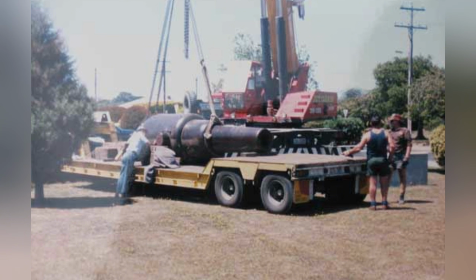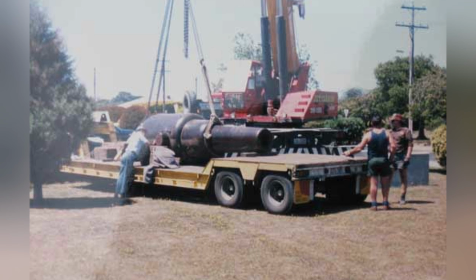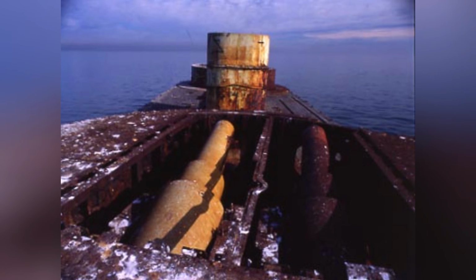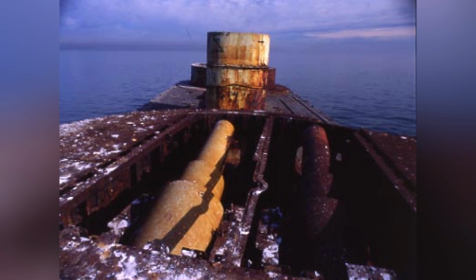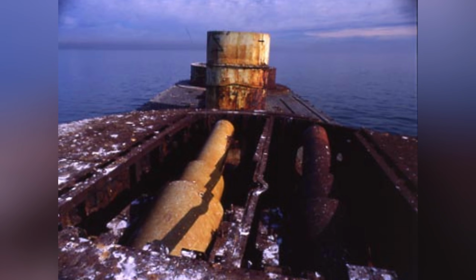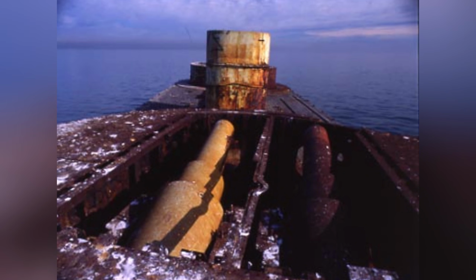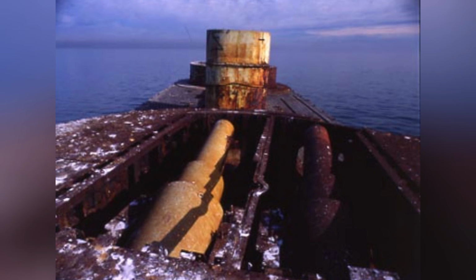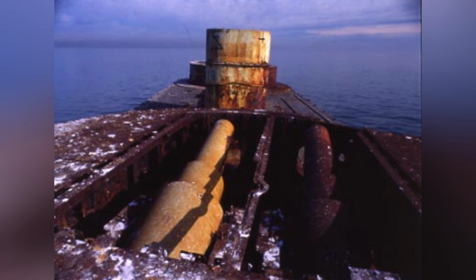The guns were gone, but the empty armored turrets and the breastwork still bore down on a lower hull that corrosion continued to hollow out. The lift had bought time, not stability, and engineers now had to shift the remaining load onto something that would not rot away. They found the final structural solution in the few elements that still retained real strength. Reports noted that the armor belt remained comparatively intact even as the thinner, unarmored structure below the waterline continued to vanish. Instead of trying to rebuild a hollowed ship from the inside, engineers focused on shifting loads away from failing frames and onto something the seabed could carry.